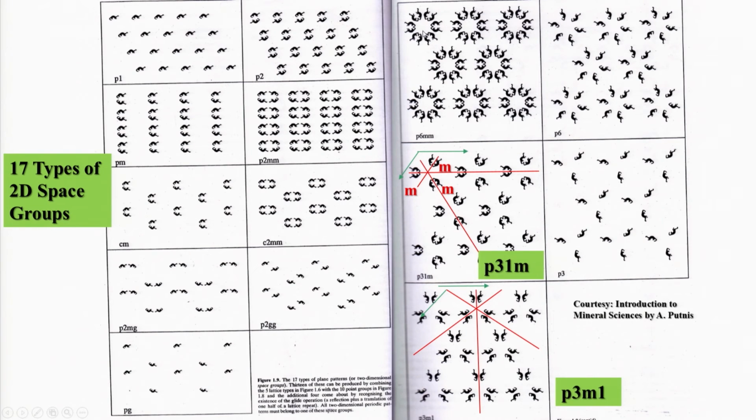In one node here, it is translated along this A, it is also translated along A, and if this angle is 60 degree, it develops this hexagonal plane lattice here. In case of P 6, there is complete absence of mirror planes, you have only a simple 6-fold axis of symmetry here. So, if this is the position of the 6-fold axis of symmetry,